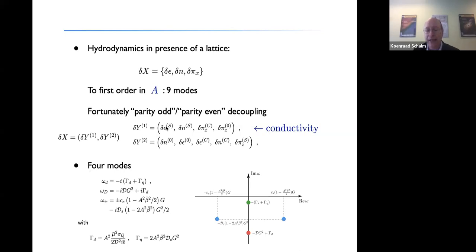And if I now do a hydrodynamic analysis of this system, I find 4 modes. This is the mode analysis at k is 0. But at k is 0, because I now have this Umklapp factor, I can still have modes that reside precisely at the lattice momentum. And you see here that 2 of these modes are the ordinary sound modes, but they're now evaluated not at an arbitrary k, but precisely at the lattice momentum g. So these are Umklapped copies of these 2 sound modes.